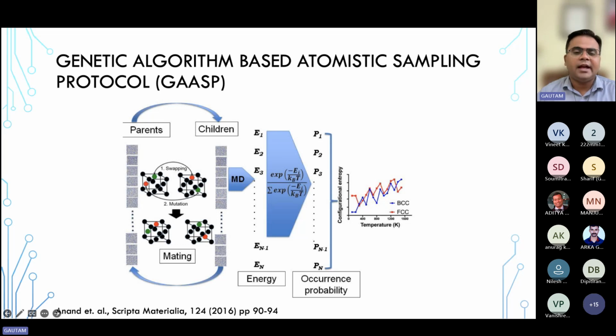It doesn't matter as long as you carry out some finite temperature sampling of a particular configuration to generate the energies, and then you can use simple formulas to generate the probability of occurrence of a particular configuration, and from there, as we have just seen, you can calculate the entropy parameter. Now, whether that is a thermodynamic entropy or not, for real thermodynamic entropy, as I told you, it requires sampling all the states which are possible, which is generally a computationally expensive proposition. That is why you have to come up with a smarter method to deal with it.